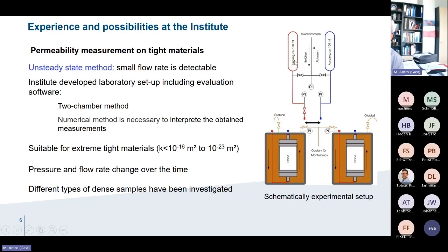And we can see any pressure differences or any pressure drop in this one. And when the pressure drop occurs here, the pressure should increase on the other side. When we have a decrease here and an increase there, that means we have communication through our core sample. We can identify the permeability. We have a suitable analytical and numerical method. We have developed that in our institute to identify the permeability. We can identify a permeability down to 10 to the minus 23 square meter, which is close to nanodarcy, lower than nanodarcy.